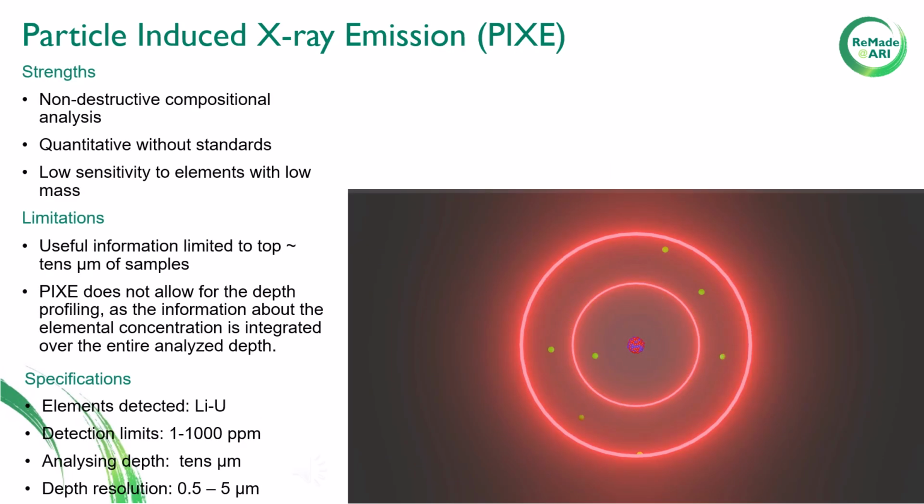Particle-induced X-ray emission is a non-destructive method in which X-ray emission is used for elemental analysis. The high-energetic proton beam excites, due to inner shell ionization, the emission of characteristic X-rays from the sample atoms. In the true sense, PIXE is not a nuclear technique, since the ionization of the atoms by the ion beam and the subsequent emission of characteristic X-rays are purely atomic electromagnetic processes. A limitation of this method is that it does not allow for depth profiling in a single measurement, as the information about the elemental concentration is integrated over the entire analyzed depth.